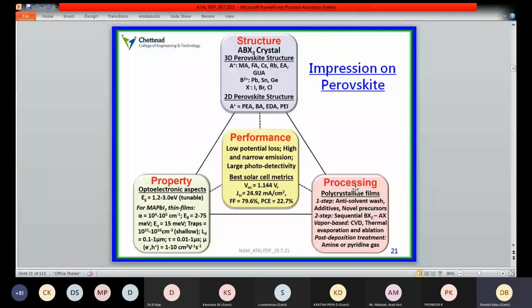We can easily fabricate this perovskite inside the glove box and outside the glove box also. So we can easily fabricate at ordinary room temperature. Some perovskites are not able to form perfectly, but most of the other kinds of perovskite material are easily able to be fabricated and processed at room temperature.